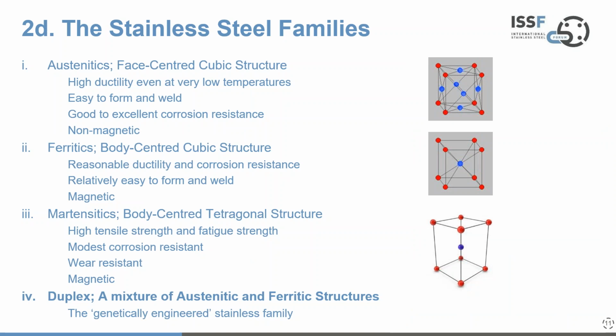So the austenitic group, which is probably the biggest and most familiar sector, at an atomic level is based on a face-centered cubic structure where there are many atoms within the cubic array, as shown in the little diagram on the right, with an atom at the center or middle of each of the 6 faces of the cube, as well as at all the corners. And that gives this great ductility performance even at low temperatures. These grades are easy to form and weld, good to excellent corrosion resistance, and non-magnetic.